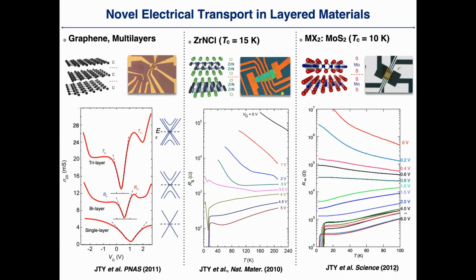Taking this ion gating, we apply it to many different 2D materials. So this is a bit of an overview of the previous work. Then we can actually tune the carrier density by a large amount so that the Fermi surface shifts significantly. So in the bilayer and trilayer cases of graphene, you can shift the Fermi surface so much that you start to meet the second subband, and then you get these features in the transfer curve.